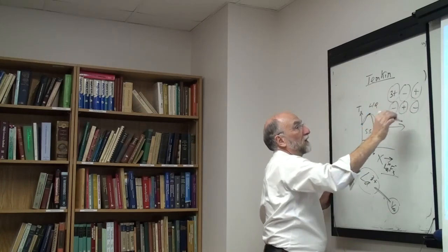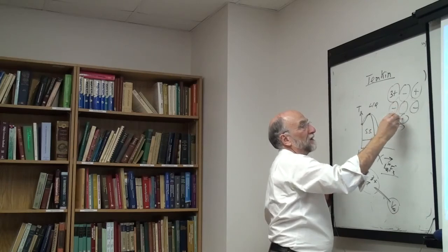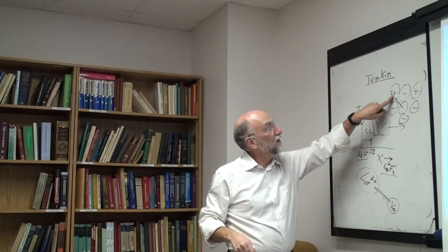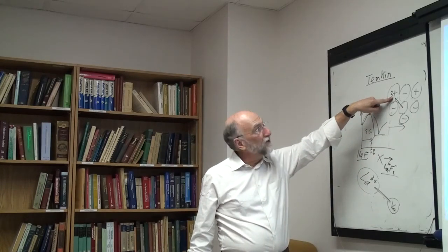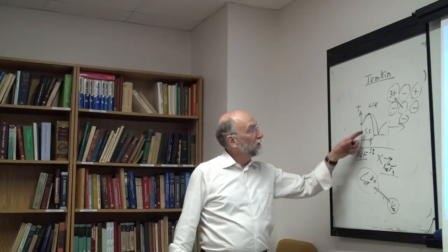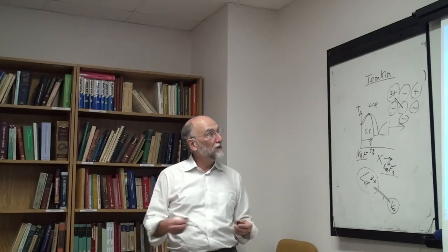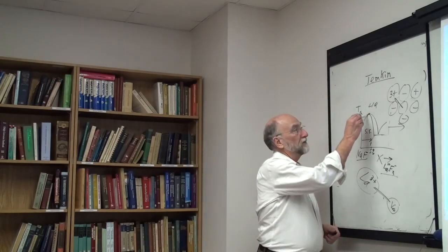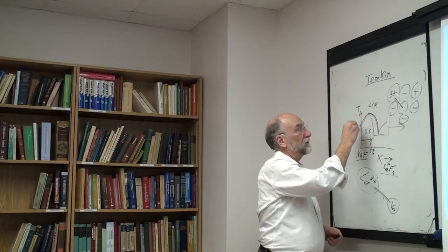If I put a lanthanum here with 3 plus and a vacancy here, then the vacancy and the lanthanum tend to try to get next to each other, because the lanthanum has an effective positive charge relative to the neutral lattice, and the vacancy has an effective negative charge relative to the neutral lattice. So they tend to form pairs, and then you're back to one new particle. You're not forming 3 particles, you're forming 1. But in very dilute solutions, the entropy always wins, and the vacancies and the 3 plus ions go their separate ways, and they add three times as much entropy as you get in the liquid. So you very often get this entropic stabilization up here.